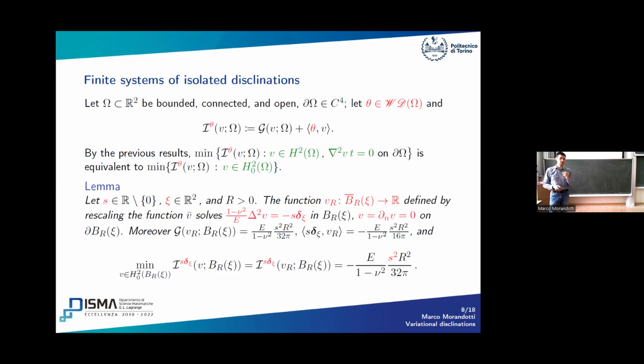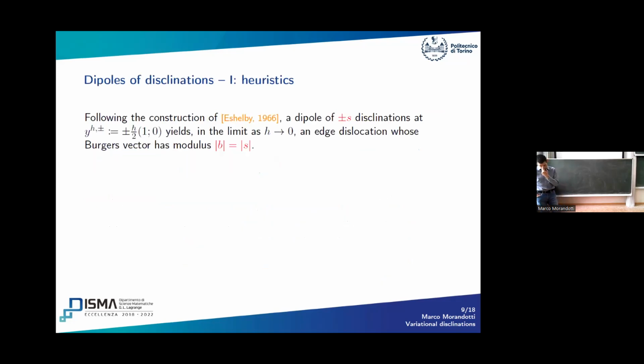All right, so the identification of the importance or the magnitude of a dislocation or disclination must be done in a way that we rescale the energy, we renormalize it, to clean it from the part that we know explodes to infinity in the way we know it explodes to infinity, and then to see what's left. And then precisely that part will be what allows us to identify the energetic contribution of the defects. And I will come to that later when we do some rescaling.